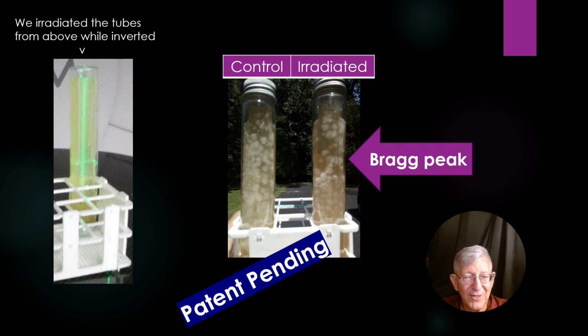Now, when we took it out and started looking at it, we inverted the tube such that the cap is at the top now. And lo and behold, if you compare the control, we only had one control and one test here. The controls had pretty much uniform growth and fairly thick growth of whatever this is.